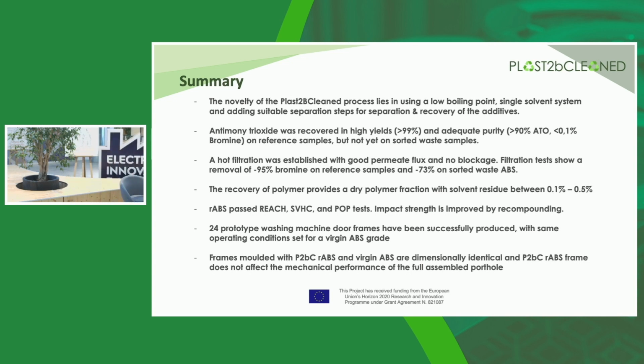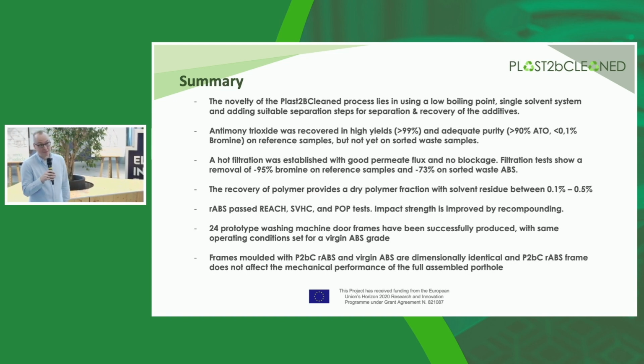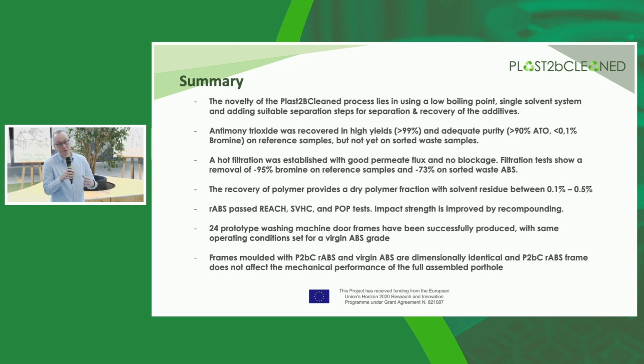Yes. Precipitation using an anti-solvent is a well-known method. We wanted to. It is a good process. It has its benefits. It has some drawbacks, and we wanted to go a different way. When you use precipitation, you usually end up with a very sticky material that's hard to filter, while if we stay in solvent, the filtration is easier, and later on, the spray drying turns out to be, hopefully, a more energy efficient way of drying the polymer material. I hope I answered that question.